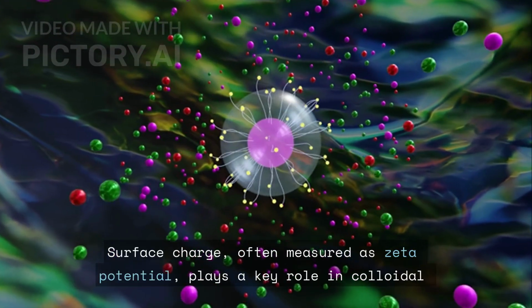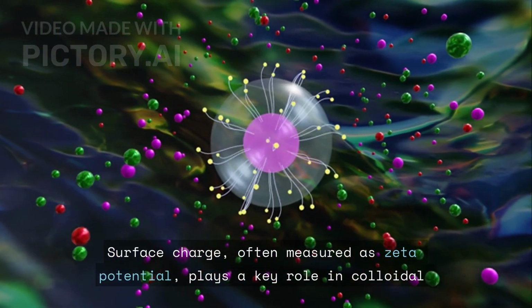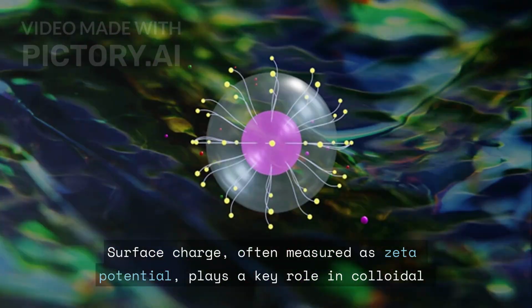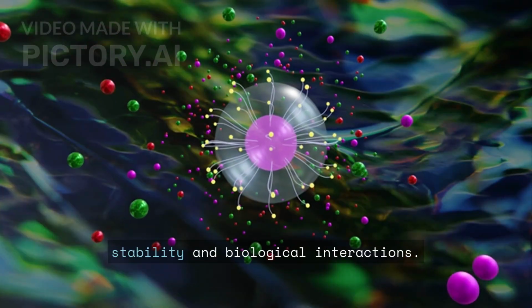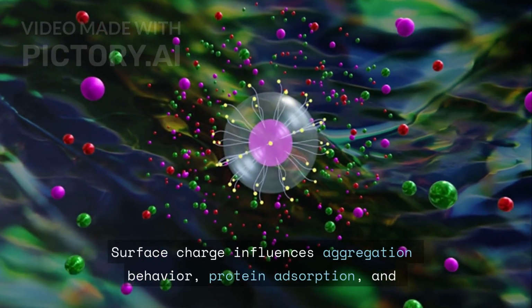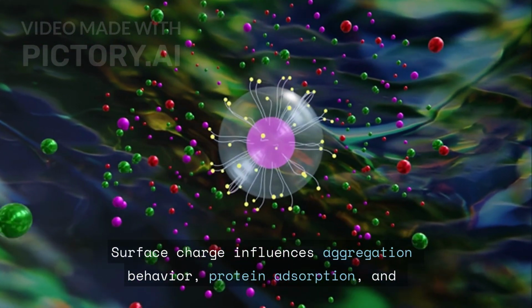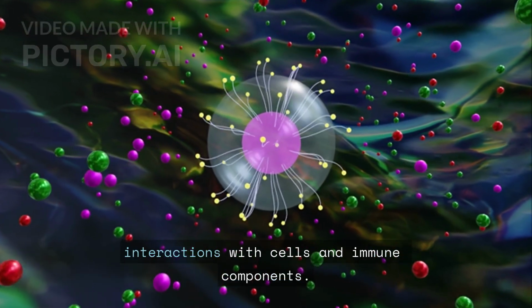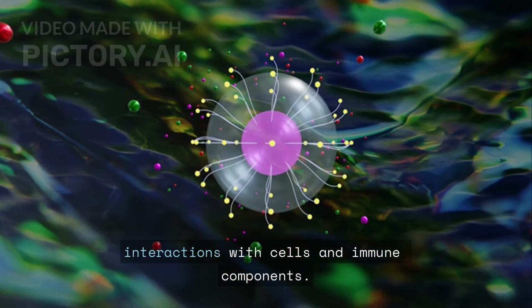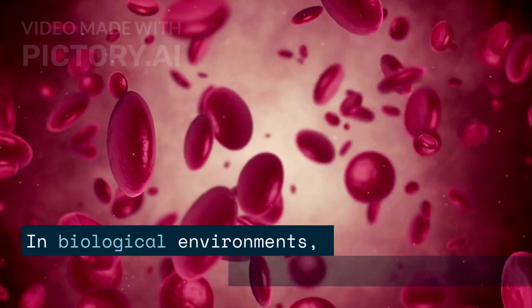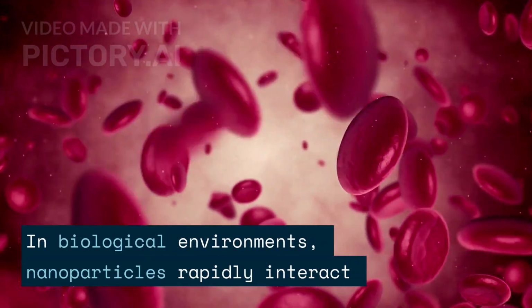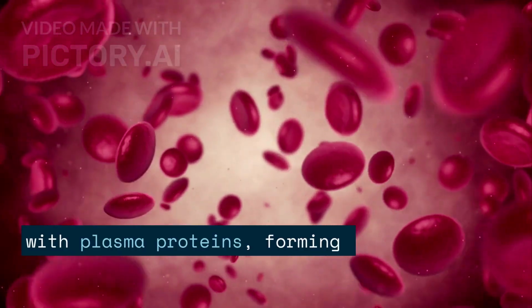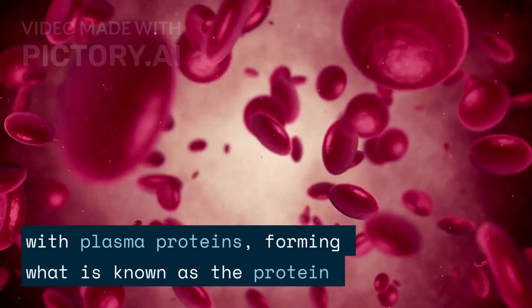Surface charge, often measured as zeta potential, plays a key role in colloidal stability and biological interactions. Surface charge influences aggregation behavior, protein adsorption, and interactions with cells and immune components. In biological environments, nanoparticles rapidly interact with plasma proteins, forming what is known as the protein corona.